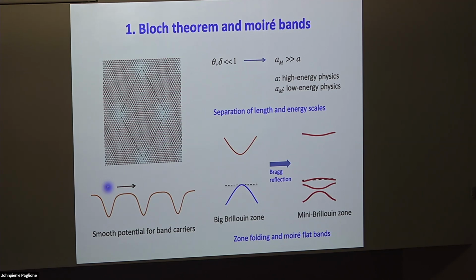The other is that these materials are relatively soft. When you put them together, they can have a three-dimensional reconstruction, like Dave Manders mentioned yesterday. Because the energy gap of the system is strain dependent, when you have a periodic modulation of the lattice structure, you can think of it as a periodic strain field. The band gap also depends on the strain, so that acts like an additional periodic potential to the system. So there are usually these two major contributions to the Moiré potential: one is related to the atomic or lattice reconstruction, the other is the interlayer tunneling.